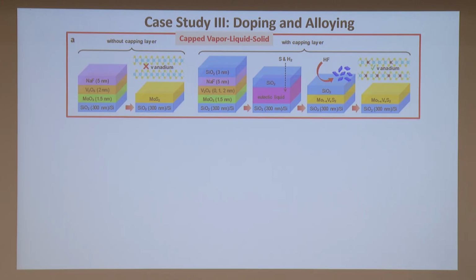We can start with what we do for molybdenum disulfide and introduce the third element. But it turned out my student kept telling me that she cannot find any vanadium. We tried to do vanadium doping, and she cannot find vanadium after she did this. Okay, so eventually we found out we lose vanadium because there is a low melting temperature liquid form during the process, and they all evaporate. So this is not trivial at all. She spent all her master thesis trying to fix the vanadium in. So we do capping.